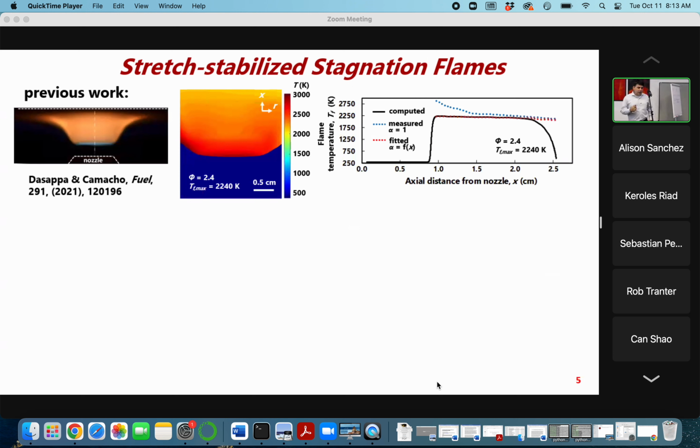In our previous work, we showed that indeed these flames are hotter than usual laboratory flames and engines. And we're still working on improving this temperature method because you can't put a thermocouple in these flames. That will just cause a lot of heat loss, which will not give you the true flame temperature. And so we did this optical pyrometry method by analyzing the soot emission, the radiation from the soot. And